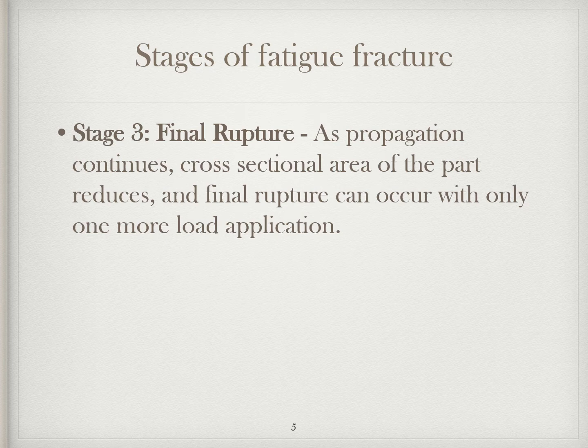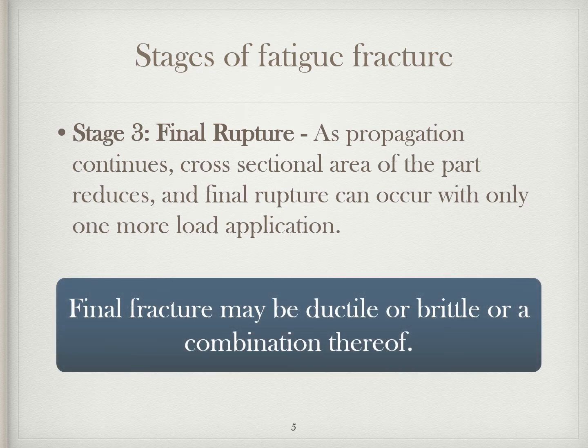Actually, stage 3 is not fatigue at all because the fracture mode may be either ductile, that is with a dimpled fracture surface, or brittle, that is with a cleavage or perhaps even intergranular fracture surface, or any combination thereof depending on factors such as the metal concerned, the stress level and the environment. However, the failure analyst must pay careful attention to the size, shape and location of the final rupture area because it can greatly assist in understanding the relation between the stresses on the part and the strength of the part. They can also indicate imbalance and non-uniform stresses.